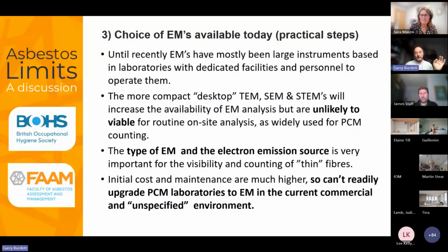And the reason for that is that we had different counting rules in those days. If I counted the same thing by TEM, and these were for direct analysis, I could count 10 fibers by one structure by TEM and 0 fibers by PCM, because we wouldn't count fibers attached to particles bigger than 3 microns, and so on. So these are probably the worst case.